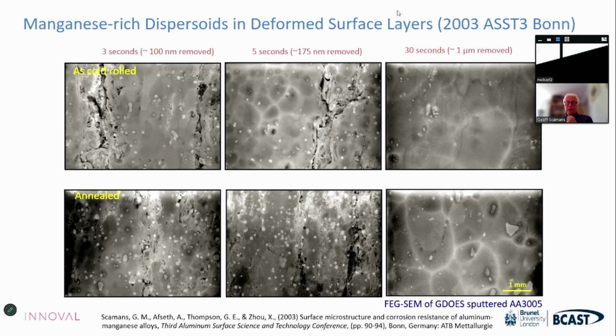And this is where we were doing some clever stuff, where we were using ion etching to expose the surface and looking at sequential observation in a fairly high resolution scanning electron microscope to see what was going on. These techniques have become much more sophisticated since 2003, but they really show the value of the progressive etching through surfaces and sequential examination in various microscopes.